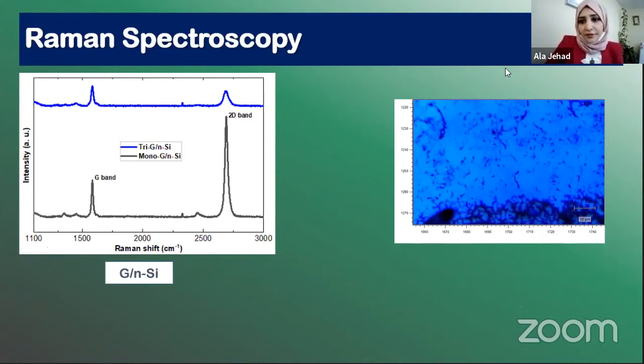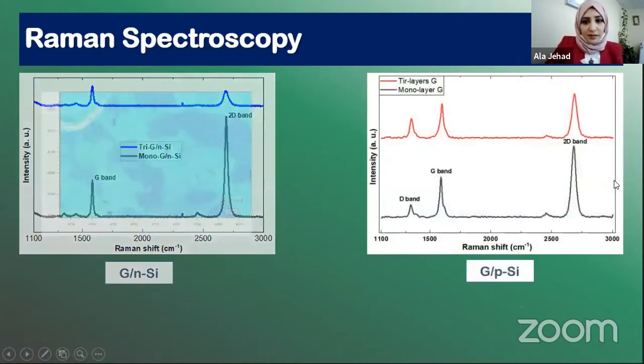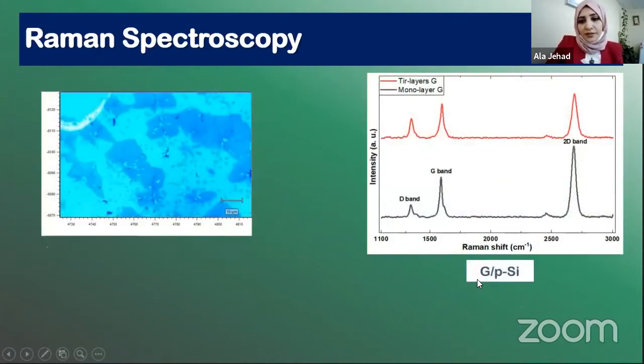Here is the image from Raman. When we use the Raman microscope, we can see we still have small points, which indicate the PMMA residue in the sample. Here is the second sample. We transfer graphene on P-type silicon, and again here we transfer monolayer, and here when we transfer trilayer, we can see we have some defect, increased defect intensity. And still we can see here we have almost monolayer, and here we have multilayer.